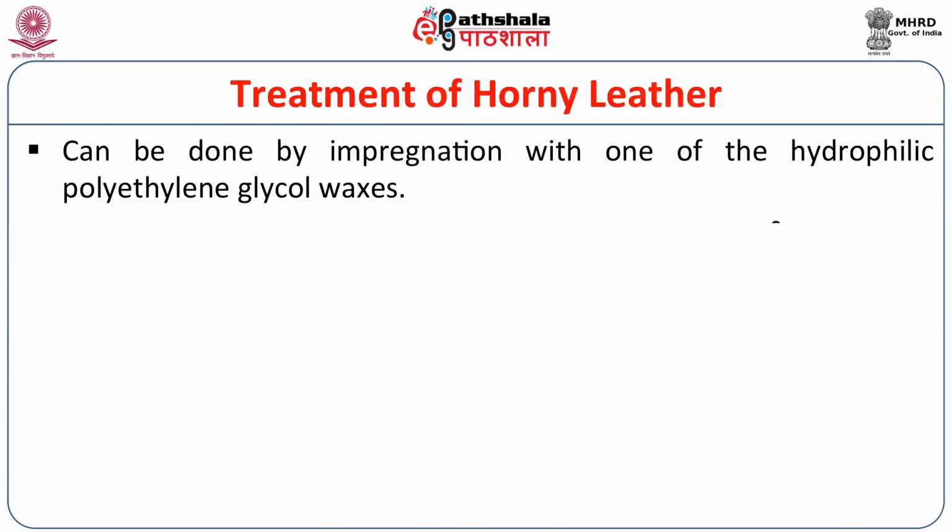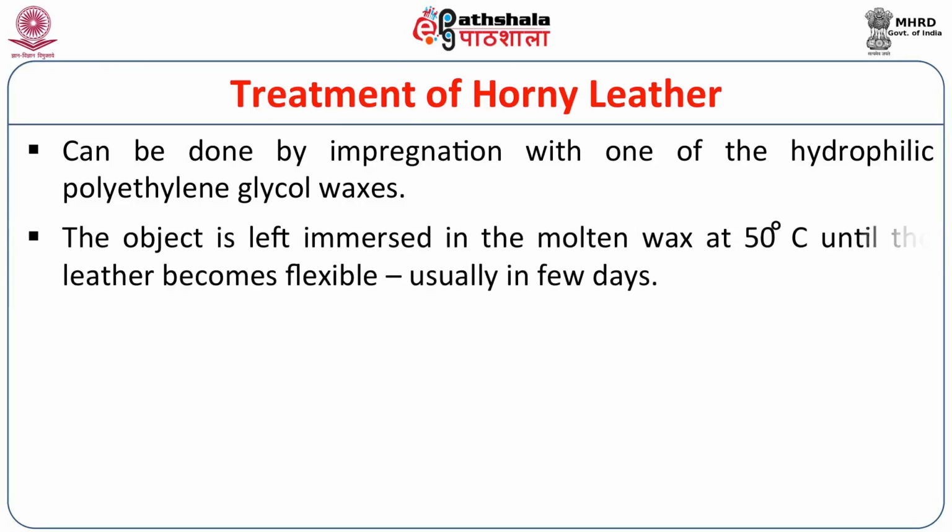For the treatment of horny leather, when the leather is very dry, it can be done by impregnation with one of the hydrophilic polyethylene glycol waxes. The object is left immersed in the molten wax at 50 degrees centigrade until the leather becomes flexible, usually in a few days.